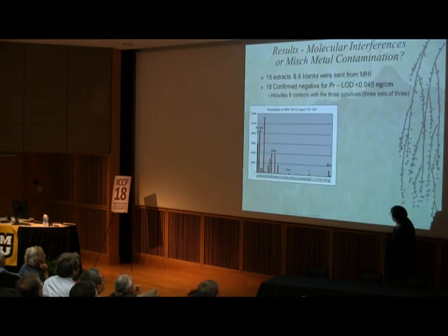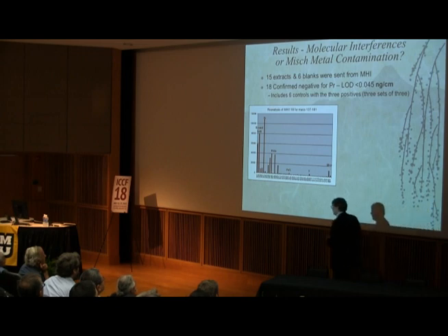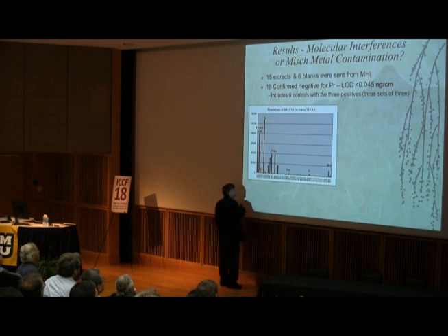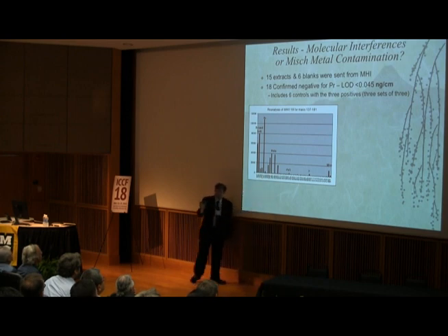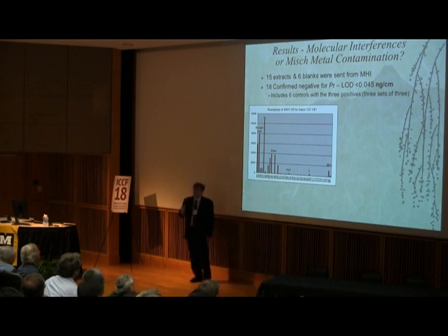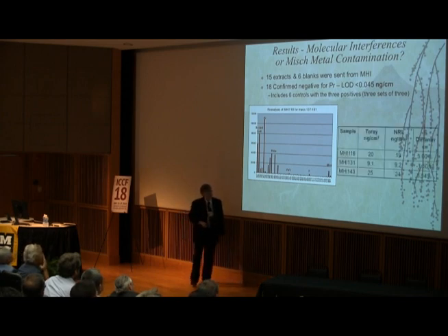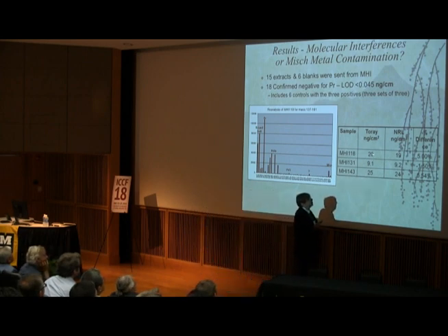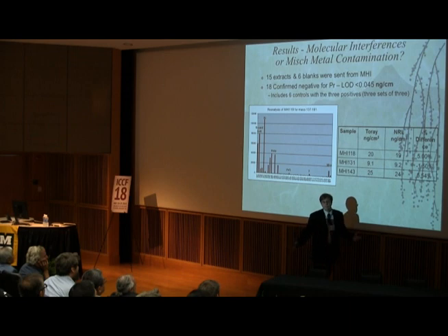Now, MHI took that one extract, they analyzed it in their laboratory, and they sent it to NRL, and we analyzed it as well. What did we find? Praseodymium. No lanthanum, no cerium, no neodymium. Pure praseodymium. Looks very good. Not only that, we were very happy. This is a commercial laboratory, Toray. They found 20 parts per billion. We found 19. They found 9.1. We found 9.2. They found 25. We found 24. Hey, we're doing pretty good.